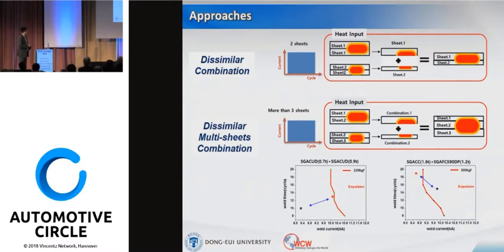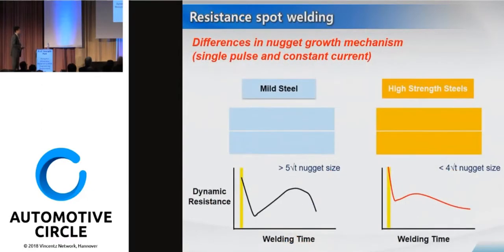This is the welding current and welding time, and this is the expulsion current limit for this combination. And with this calculation, I came up with this welding current and welding time, which is right before the expulsion current and time. And the other case was also a very similar case. So it was validated. I want to emphasize this thing before I move on to the pulsed current profile. There are actually differences in nugget growth mechanism between the mild steel and high-strength steel.